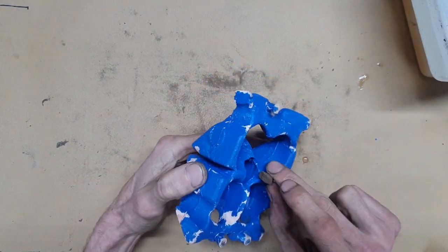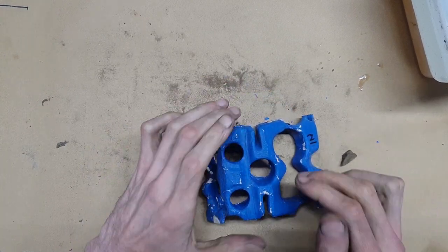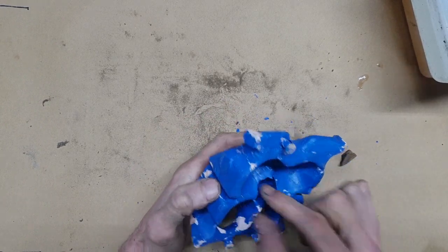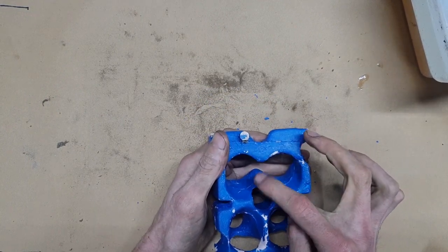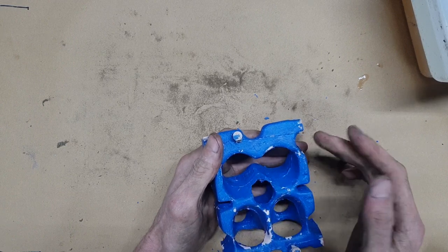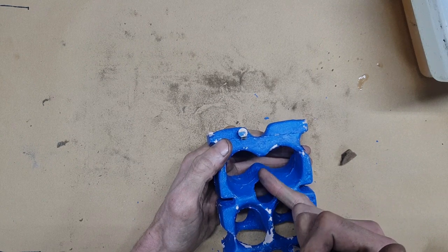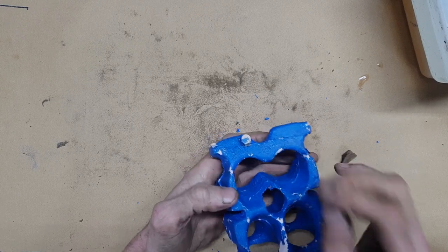So that's that. Now, getting on to what the video was actually about, 40 minutes later. The older cylinder heads were just done this way. You needed robust sand cores to be able to put them in and handle them without them breaking. The result is that you need a huge amount of aluminium here. You can see how strong this needs to be. On the exhaust side, they didn't bother with a bridge at all because the valves were so big. They're bigger than the intake side, as you know. The valves were so big they couldn't put a thin core down here because it would be too fragile and risk breaking.